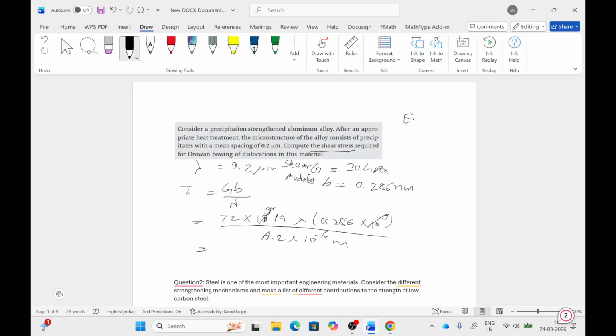So elastic modulus is 72 GPa for aluminum, and shear modulus is 30 GPa. When we put 30 here, that will result in 42.42 into 10 raised to power 6 Pascal, that is 42.42 megapascal.